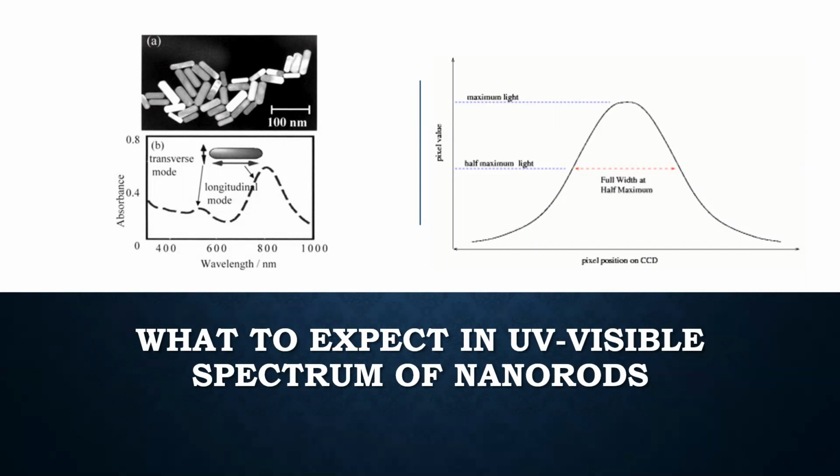As can be seen from the figure, the absorption in green illustrates gold nanorods, in which a lower peak at 512 nanometers depicts a transverse peak, while a stronger peak at 780 nanometers shows a longitudinal mode.